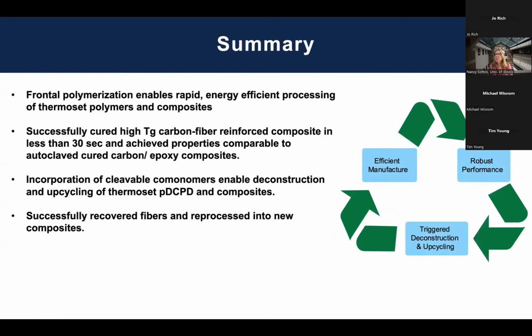And so just let me end there, hopefully convincing you that frontal polymerization is an interesting process for composites. We can make them quickly out of autoclave with nice properties. We've been able to impart this cleavable comonomer that enables deconstruction of the neat resin and the composite. And we've successfully recovered fibers and reprocessed them into new composites with comparable properties.